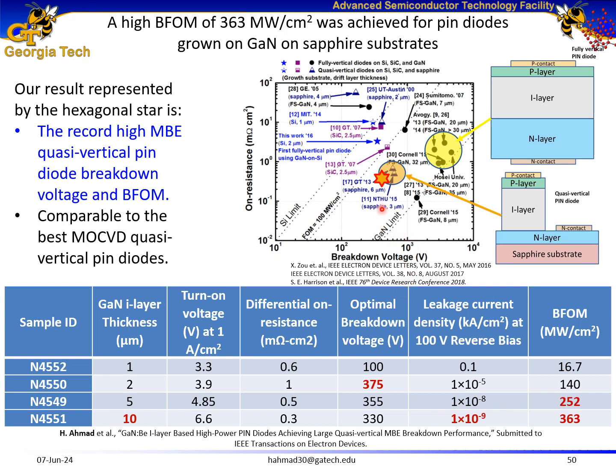And by comparison of our breakdown performance with the state-of-the-art quasi-vertical devices, we are comparable to the best MOCVD-grown quasi-vertical devices, and we are the only group in the state-of-the-art MBE performance in terms of quasi-vertical devices. We achieved record breakdown performance and also record Baliga's figure of merit for MBE-grown quasi-vertical devices.